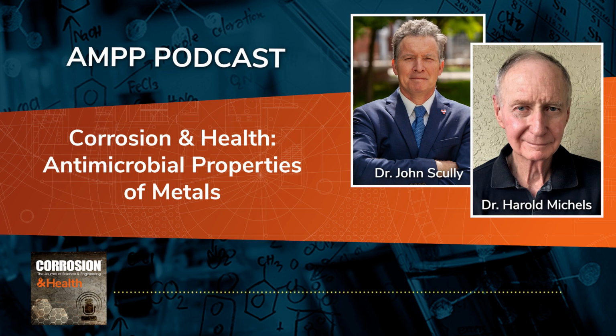There are other kinds of things, like the titanium dioxide is a photocatalyst that actually basically splits water. And so you get sort of the oxygen radicals and oxygen and hydrogen out of that reaction. So that's an altogether different process than the one we're talking about here, although it is an electrochemical process. But the main source is the copper ions from a corrosion process, where you've got some cathodic reaction and some anodic reaction, which is the dissolution of the copper.